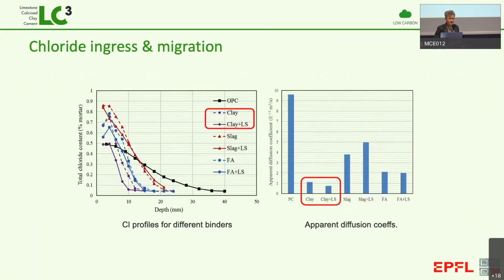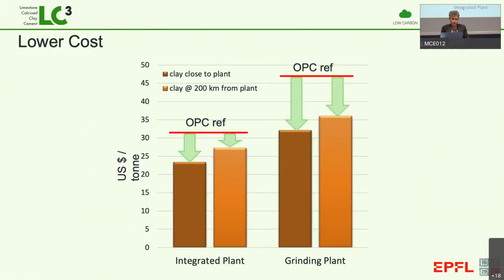In terms of chloride ingress, this black curve here shows you the chloride that has penetrated into the reference Portland cement after just 6 months. And the mixtures which contain slag, shown here in red, they're improved. The mixtures with fly ash, again, they're better still. But the best of all are these mixtures with the calcined clay and the calcined clay with limestone. And then people say, well, what does this cost? Again, good news, because it can be cheaper to produce than the existing materials.